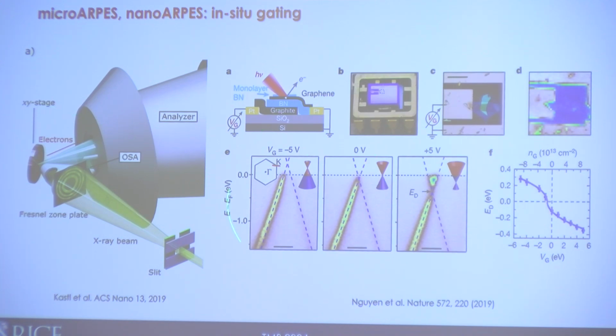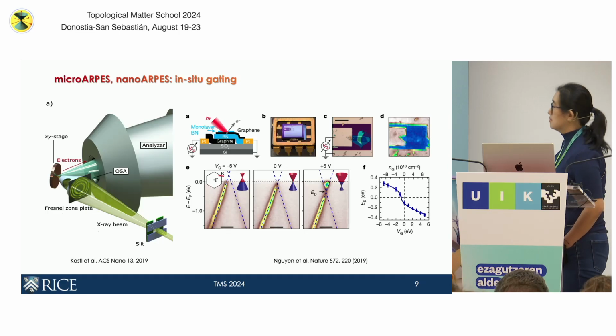So in this construct, which is work done by Dave Cobden's group in collaboration with Eli Rotenberg, they put this graphene on top of hBN, which really provides the doping and also the physical flatness under the beam, where they can actually measure. And this is the first time they can see that with in situ gating, they can measure dispersion. Since then, there have been many groups that have utilized this technique to measure exfoliated flakes and also gated 2D materials. So I think this is a very nice development in the field.